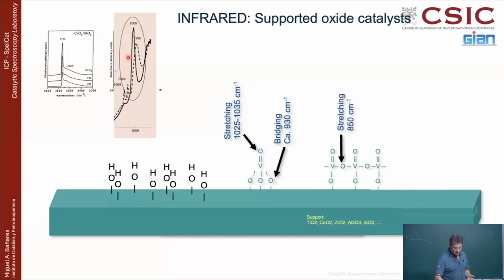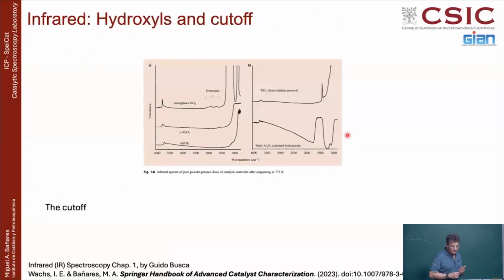If you have more, these species will start to polymerize. They will get polymers because there's one vanadium there, but if they are nearby, there will be an interaction, they will be sharing oxygens, and then you will get bridging oxygens not only to the support, but among themselves. And this will be not V-O-support, but V-O-V, or Mo-O-Mo, whatever is the cation that you have there. And they will have another vibration like 800 plus or whatever. Now, that's ideal.